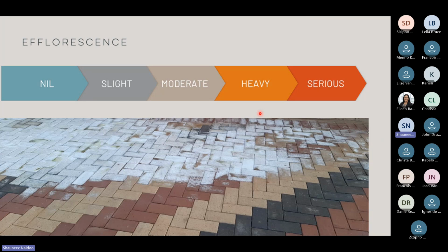And most of the time we are able to see, because if you look at this specific picture, if it was coming from the pavers, it would be everywhere. But you can see it's clearly on a certain section of the flooring. So then we do the necessary investigation. We've got an independent lab that can test exactly where the efflorescence is coming from. Efflorescence is not permanent. It does fade over time, and we do know how to treat it. It is basically just dry brushed away from the building, because I mentioned it is a soluble salt. So if you do wet it, it will literally just dissolve and over time dry and then settle again. So we do have a way to treat efflorescence if it is coming from the pavers. If it is coming from the soil or the sand or so forth, then obviously we look at those sources.